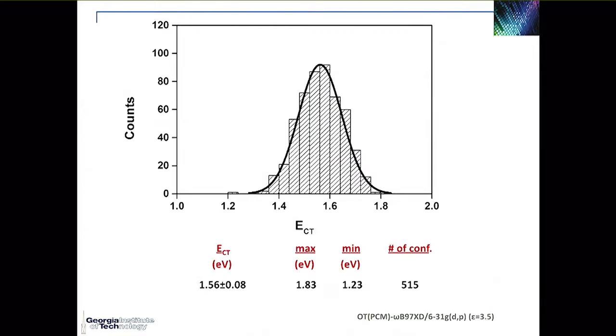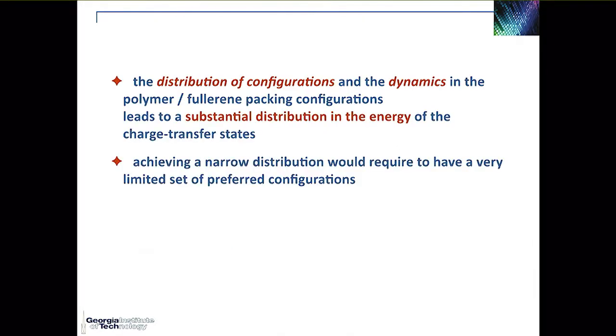And even if the standard deviation is pretty small, of course, the whole issue is that you have quite a lot of those CT states at lower energy. If the CT state is low in energy, you get a lower open circuit voltage. So the distribution of configurations and the dynamics in the system, the individual vibrations, as well as the differences in the morphologies that you can get in the polymer fullerene configurations, does indeed lead to a very substantial distribution in the energy of the charge transfer states.